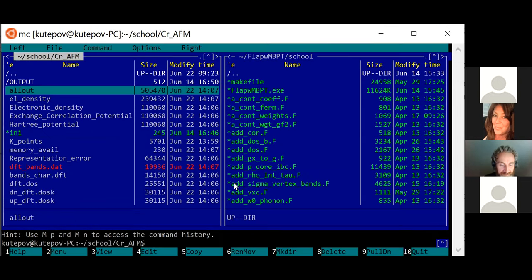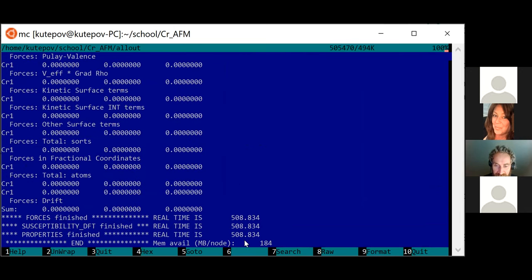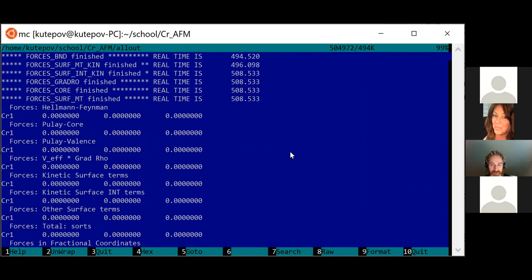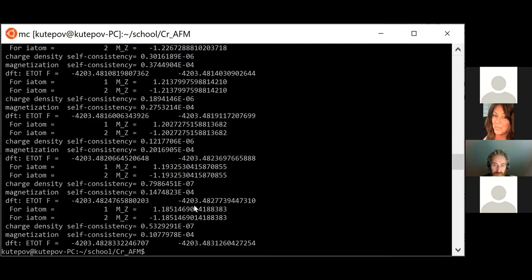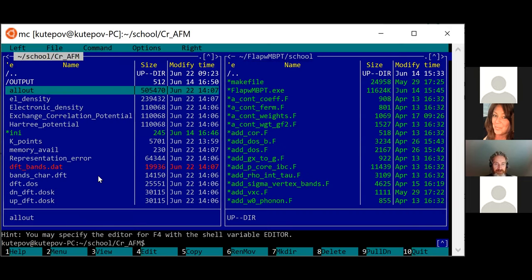I ran the antiferromagnetic chromium calculation in 59 seconds. Looking at the output, you can see that the two atoms have opposite magnetic moments — around ±1.18 — confirming antiferromagnetic ordering. There is not yet exact convergence, but you probably should take more iterations.